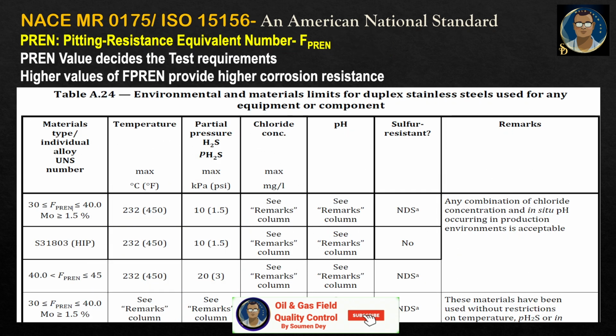So if you see this table A24, for environmental and material limits for duplex stainless steel used for any equipment or component, you can see FPREN greater than or equal to 30 but less than or equal to 40, molybdenum greater than or equal to 1.5%. The maximum temperature it can be used at is 232 degrees Celsius or 450 degrees Fahrenheit, and the partial pressure of H2S it can withstand is maximum 10 kPa or 1.5 psi. Chloride content, pH and sulfur resistance, we can see the contents at the bottom. So any combination of chloride concentration and in situ pH occurring in production environments is acceptable. So the table will give you an idea which PREN value will provide you how much resistance against the corrosion.